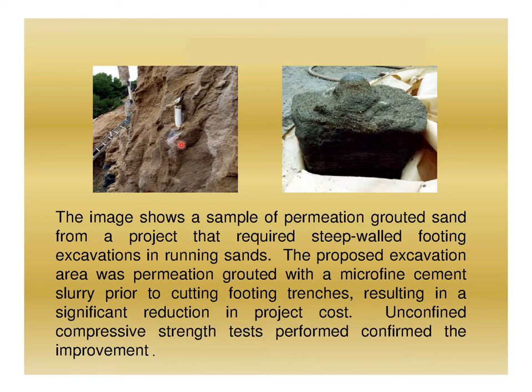Here you can see permeation grouting has been carried out. The image shows a sample of permeation grouted sand from a project that required steep-walled footing excavation in running sands. The proposed excavation area was permeation grouted with a microfine cement slurry prior to cutting footing trenches, resulting in a significant reduction in project cost. Unconfined compressive strength tests confirmed the improvement.